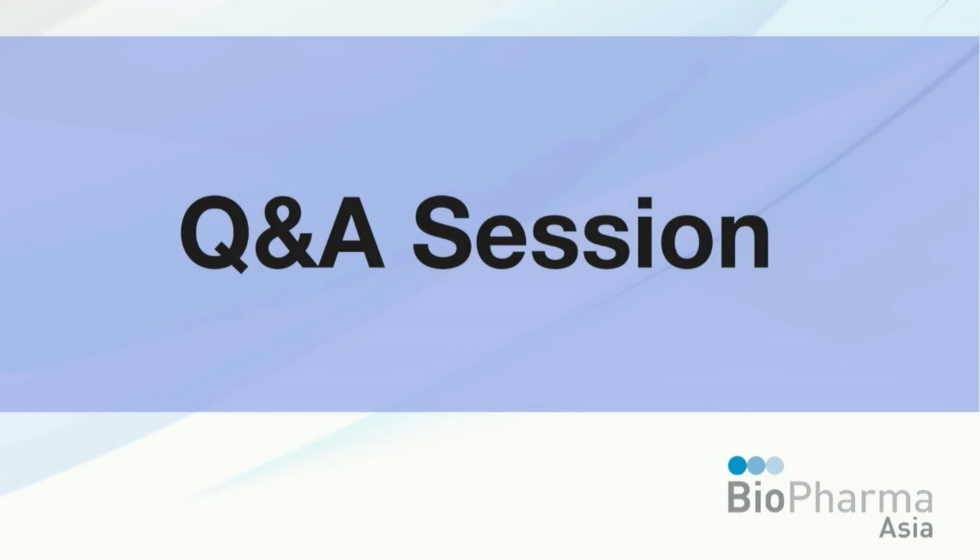Yeah, I think Ken already answered pretty well. As I mentioned in the presentation, the main techniques we use are headspace and direct injection GC, LC-MS, and ICP-MS. With these you can really get the identification and the quantitation for the extractable profile. Some bulk property testing, like NVR, UV, pH, is more like general information. So you can't really tell what comes out. You can only get very general information on the profile.